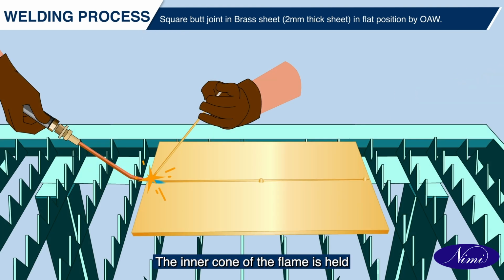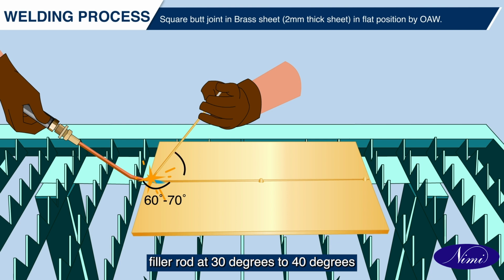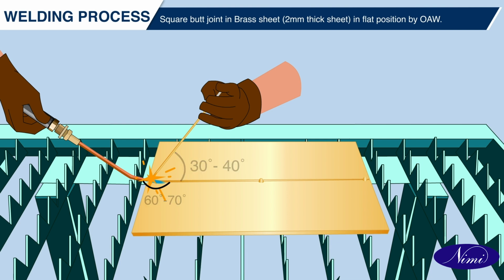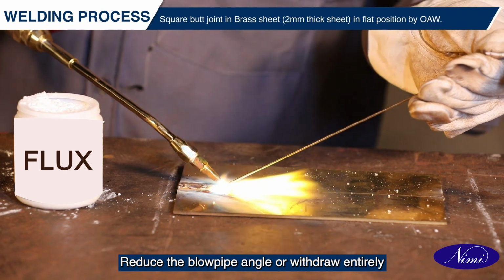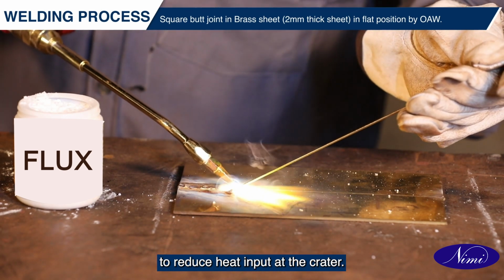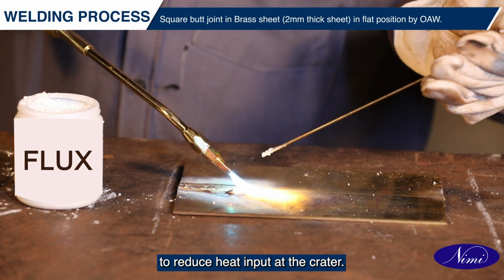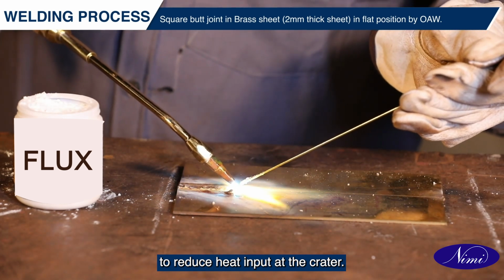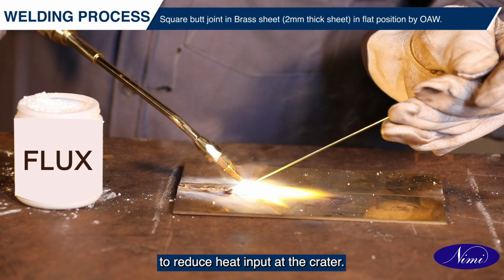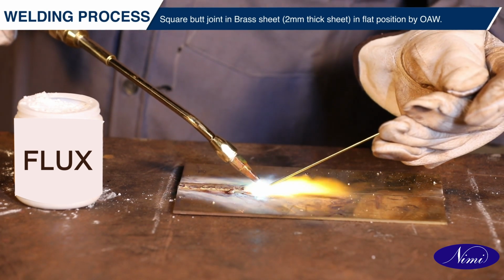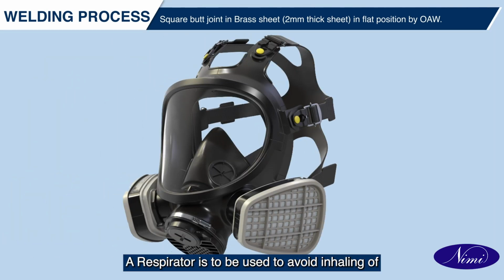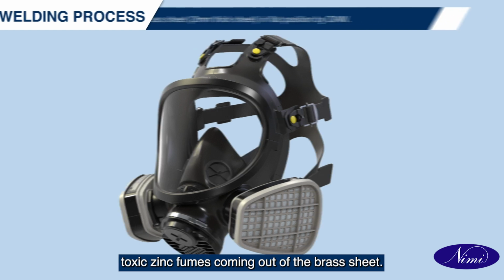The inner cone of the flame is held fairly close to the surface for the weld. Keep the angle of the blowpipe at 60 degrees to 70 degrees and filler rod at 30 degrees to 40 degrees. Reduce the blowpipe angle or withdraw entirely to reduce heat input at the crater. A respirator is to be used to avoid inhaling of toxic zinc fumes coming out of the brass sheet.